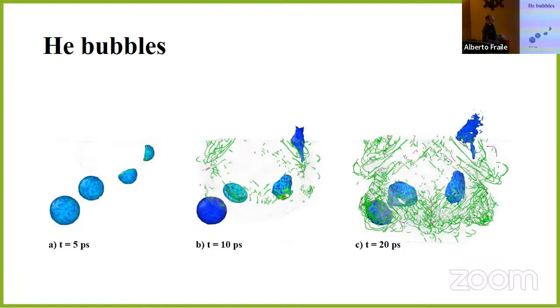And then the pressure and the shockwave will compress the helium bubbles and then they can coalesce also depending on the distance. And also, for example, this one here that was close to the surface can just break and the helium will go up. So, well, this is something for another paper, because you can analyze a lot of things here, and you need also to do a lot of simulations to have statistics on everything that is happening here. You can imagine that a lot of things are happening there. But in general, what we saw is that about 10% is the change when you have a helium bubble basically around the impact. So it's not that big a difference.